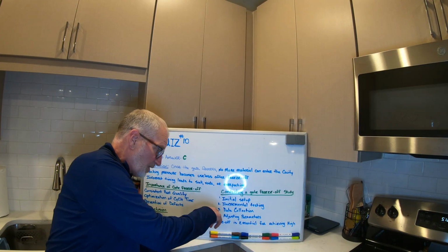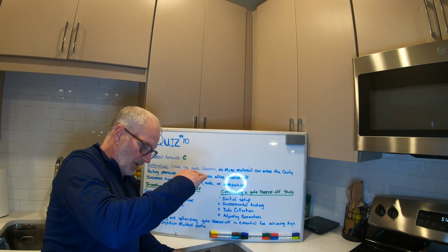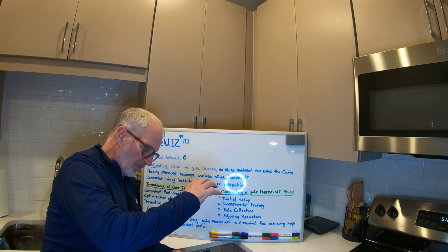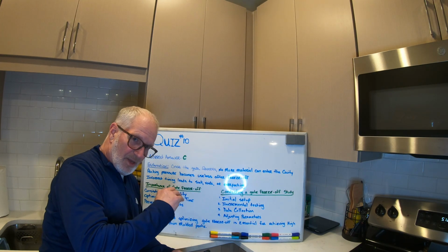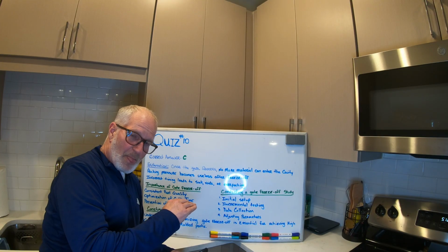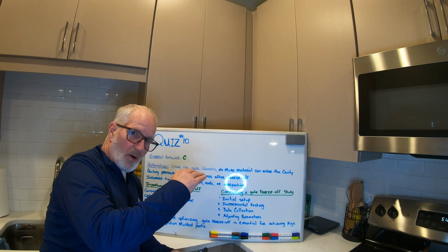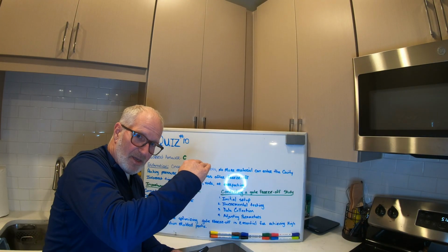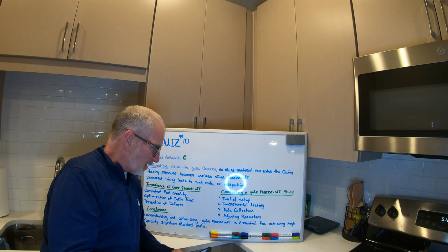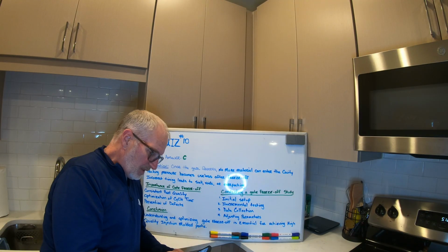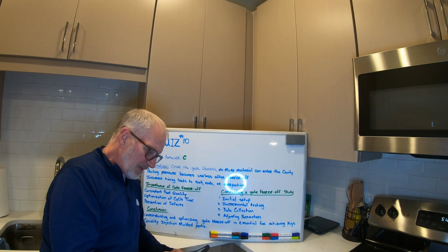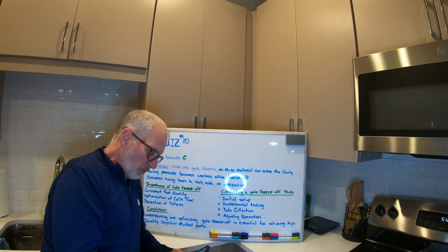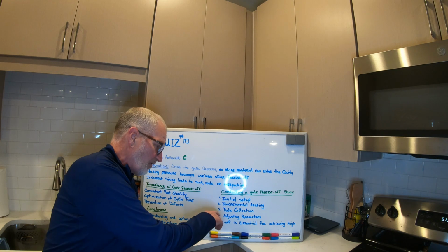gate is freezing off. So what you're doing is you're weighing your part every single time for your hold. Once the part gets to where it's not gaining any more weight, then you know your gate freeze is right there, guys. Then when you're doing data collection, you're recording the part weight and analyzing the data to find the point at which the weight stabilizes, which indicates the gate is frozen off.